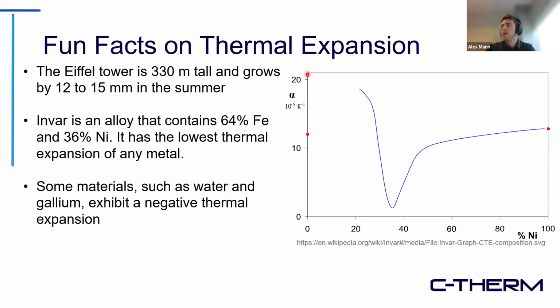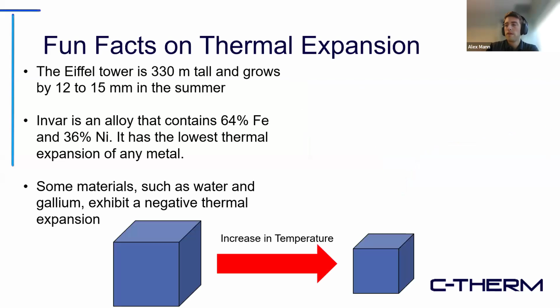Up here, we have our iron, pure iron CTE. Down here, we have our pure nickel CTE. Then as we combine them and the percentage of nickel grows, we can see we get a sharp curve where we have Invar right here. We have very low thermal expansion. That just goes to show that you can't really predict CTE sometimes, and it's based off things like crystal structure and such.